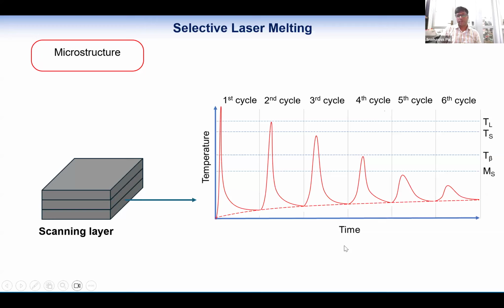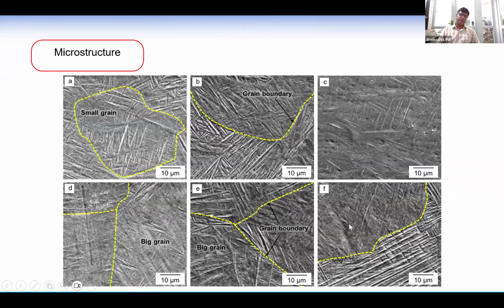Accordingly, the microstructure will be formed by remelting sometimes, or also because it is above the martensitic start temperature. So several thermal effects occur, forming martensitic needles every time. The bigger ones are formed in the beginning, and the smaller ones in the last cycles. There are a lot of differences also due to changes of laser power and scanning speed.